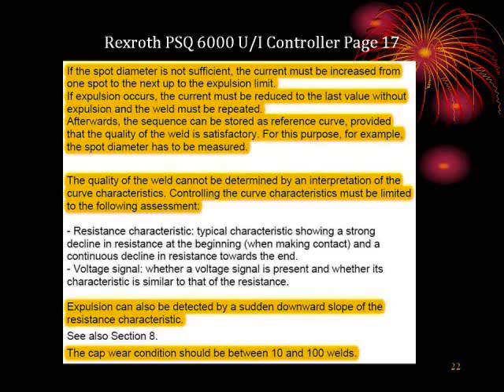The last part, the cap wear condition, which they mean the dressing of the weld cap, should be between 10 and 100 welds. If I can dress a cap every 10 welds to 100 welds, I really don't need this thing to control. All I do is welding by constant current.